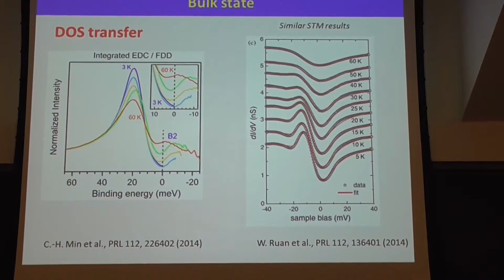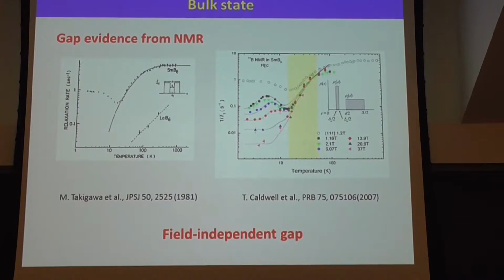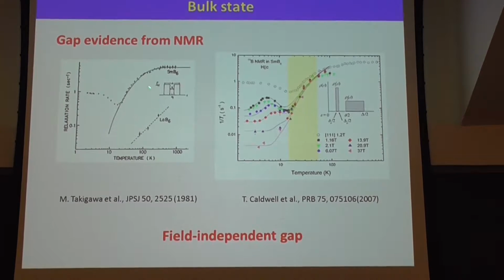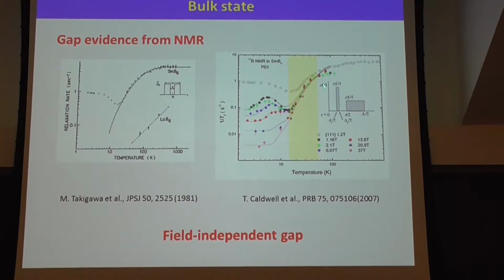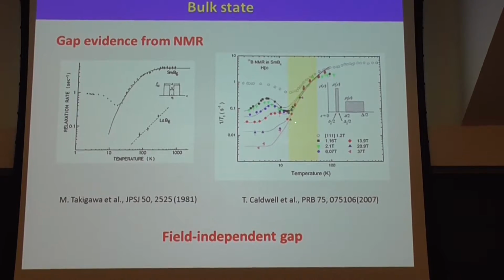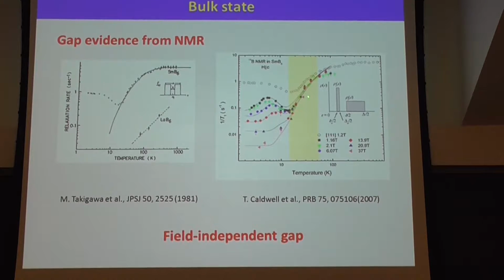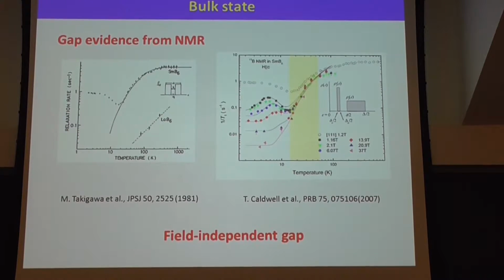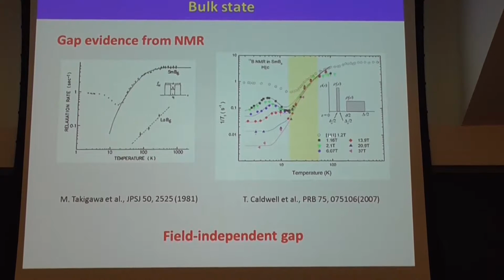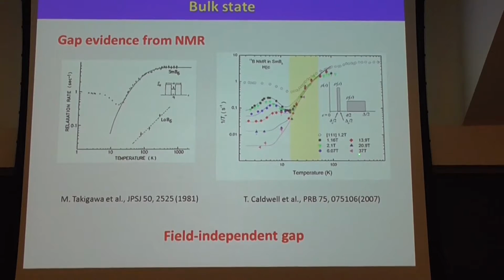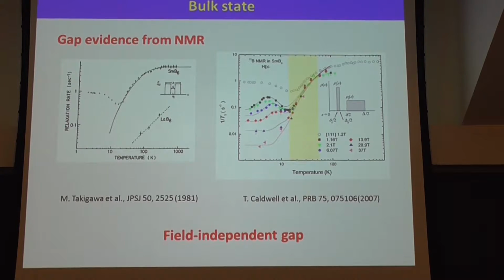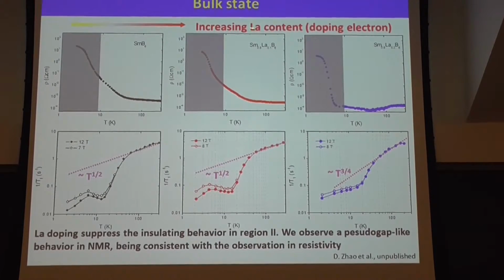This means that in this region, the gap looks like a hybridization gap. Okay? And also by NMR it shows the hybridization gap behavior in this region, from 60 Kelvin, this data here. And this gap is also independent of the field. You can see the field is from 0 tesla to 37 tesla. In this region, the gap is independent. Also, it looks like a hybridization gap.